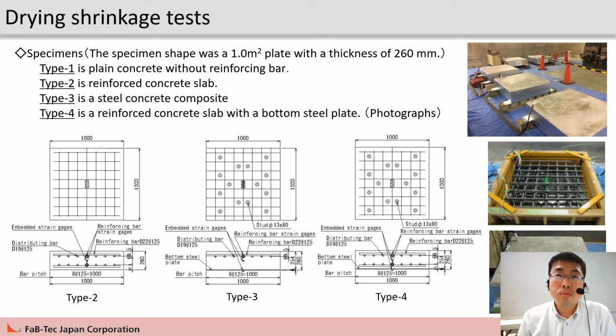These tests were performed to determine the influence of the bottom steel plate on the drying shrinkage behavior. Specimens of type 1 to 4 were installed in the basement of the Osaka Institute of Technology to maintain constant temperature and humidity. Type 1 is plain concrete without reinforcing bar. Type 2 is reinforced concrete slab. Type 3 is a steel concrete composite slab. Type 4 is a reinforced concrete slab with a bottom steel plate. The specimen shape was a 1 square meter plate with a thickness of 260 mm.